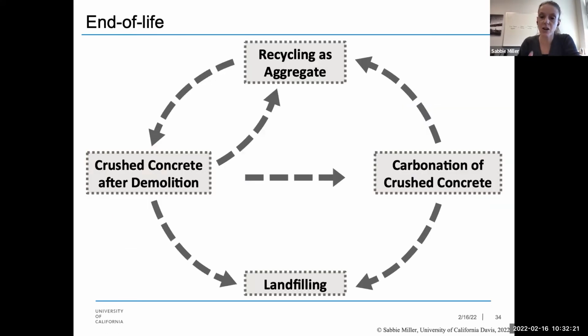In particular, what we can end up doing is using our concrete and our other hydrated cement systems to act as a direct air capture mechanism or as a mechanism to offset our demands for aggregates. Specifically, our crushed concrete can be utilized as either an aggregate or backfill. This is already a relatively common practice, and that will potentially offset our need for more cement-based materials, or at least more virgin aggregates. We also can use our crushed concrete as a direct air capture source.